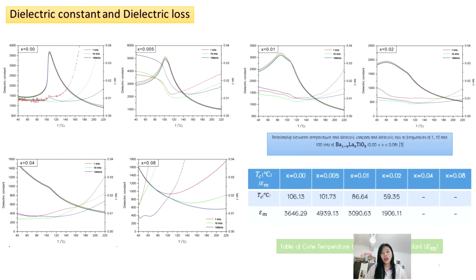Dielectric constant and dielectric loss. You can see the relationship between temperature and dielectric constant and dielectric loss at frequencies of 1, 10, and 100 kHz of barium titanate doped with lanthanum. But for x equals 0.04 and 0.08, it cannot be shown in this temperature range.